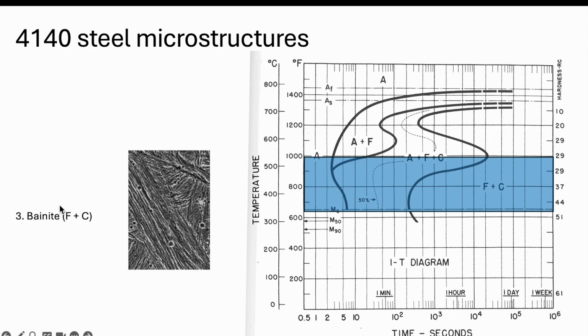And this is where we have what's called bainite. As it's shown here, the important thing to note is that the isothermal diagram itself just says F plus C, so ferrite plus cementite. So again, these are the equilibrium phases. However, instead of being in the form of pearlite, it forms into this much smaller structure known as bainite. Bainite is a smaller structure, it's harder, it has higher strength, and it's got a much finer, harder to see microstructure. So we'll look at this in the slides here in a bit.